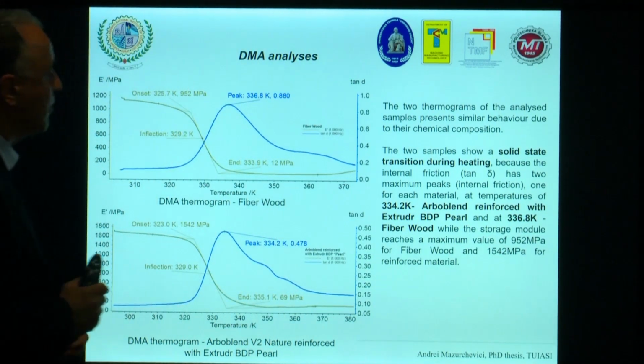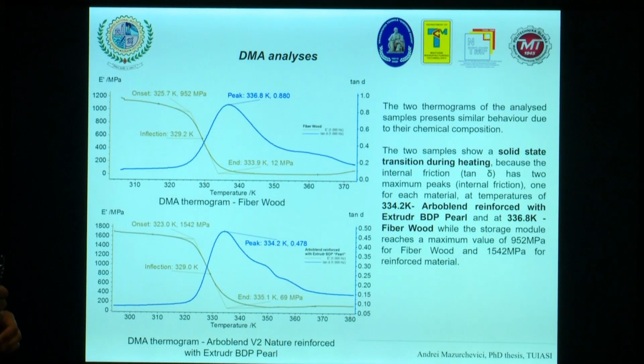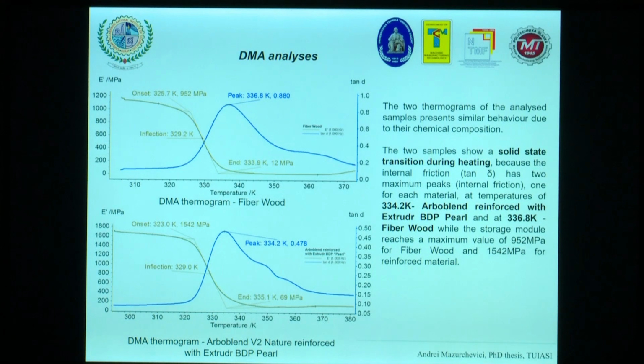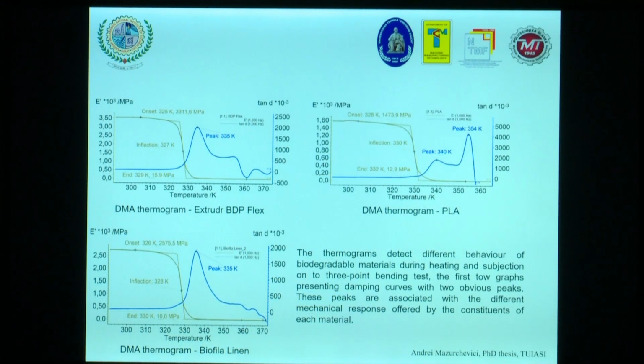So the storage modulus, you can see also for fiberwood, 952 megapascal and 1542 megapascal in case of our materials. Of course, we can talk more about the DMA diagram that you can see over there. The software shows us many other information about temperature range, peaks, and so on. The peaks must always be attributed to the other elements, especially on XRD and the other tests. But I think it's enough for today.